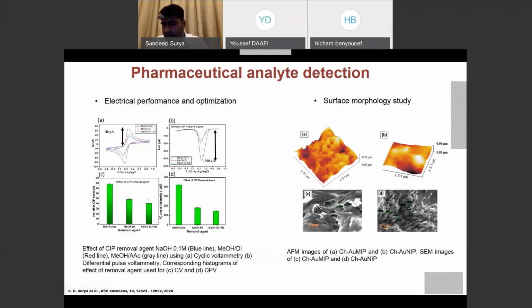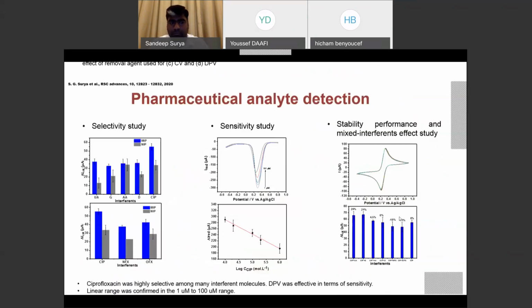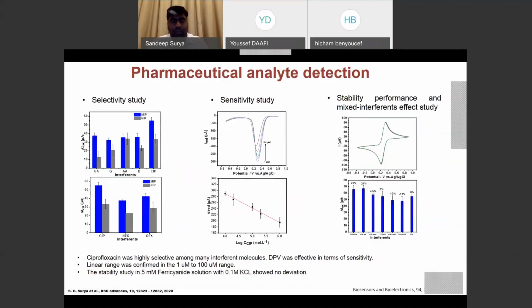Further, the confirmation has been done through the SEM images, wherein we have bigger peaks and valleys in the case of MIP over here, and more or less kind of same smooth surface. Here, the 2 micron is the resolution that has been utilized for both the SEM images. After the morphological study, we have continued with our studies of selectivity, sensitivity, and stability. In the first case, the selectivity has been done with other interference, as one can see from here, for both the MIP and NIP. So the other interference include uric acid, glucose, ascorbic acid, dopamine, and ciprofloxacin.